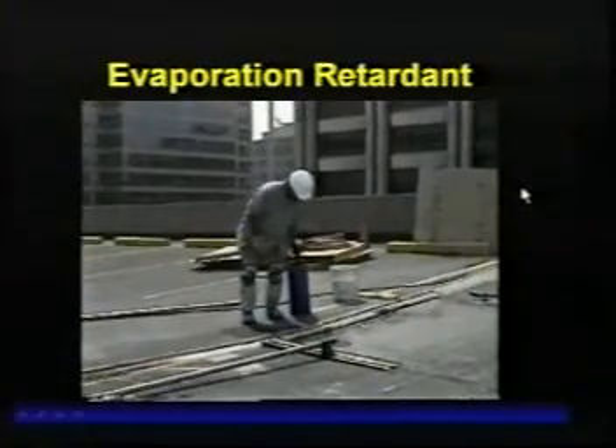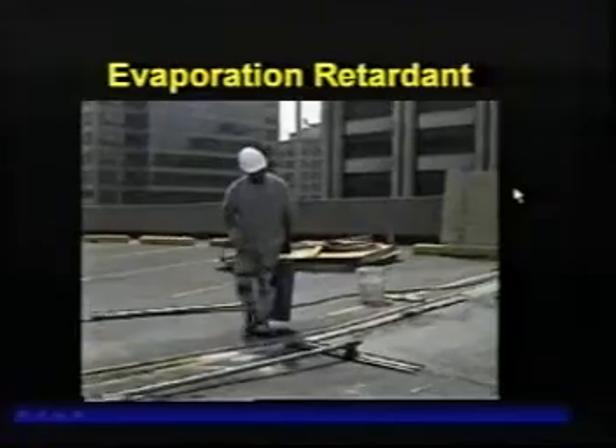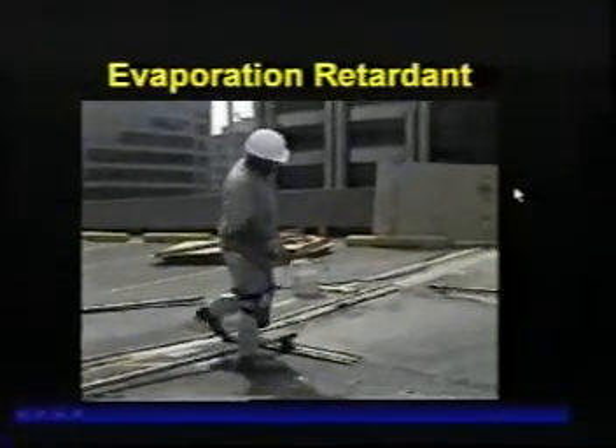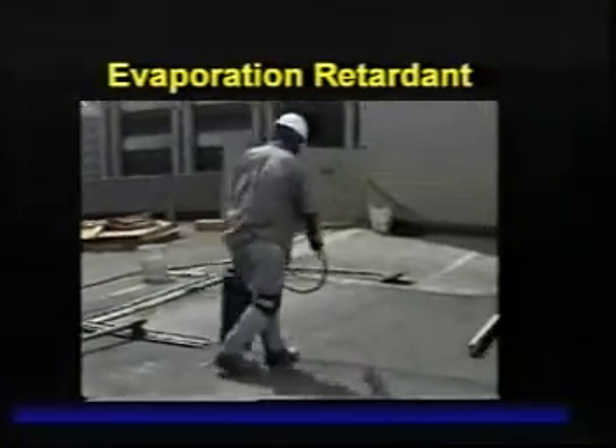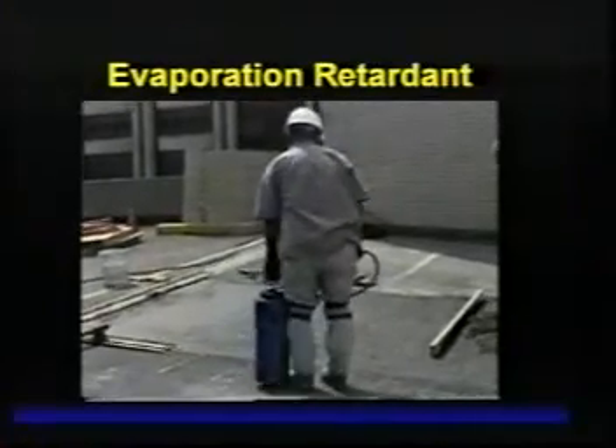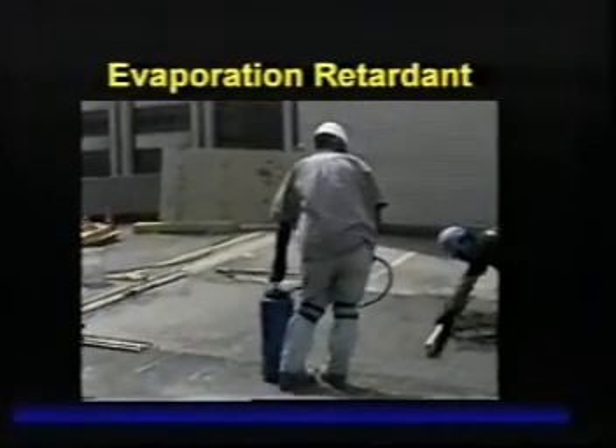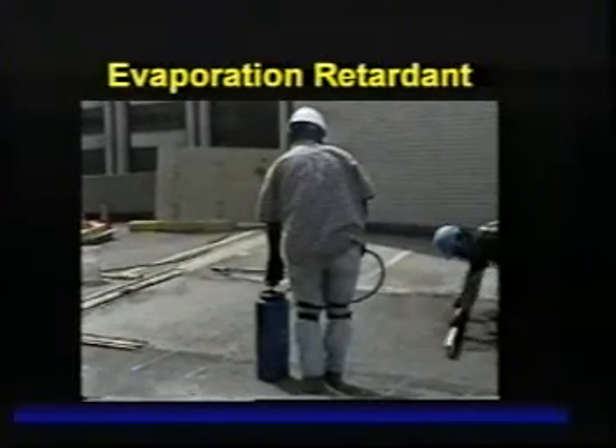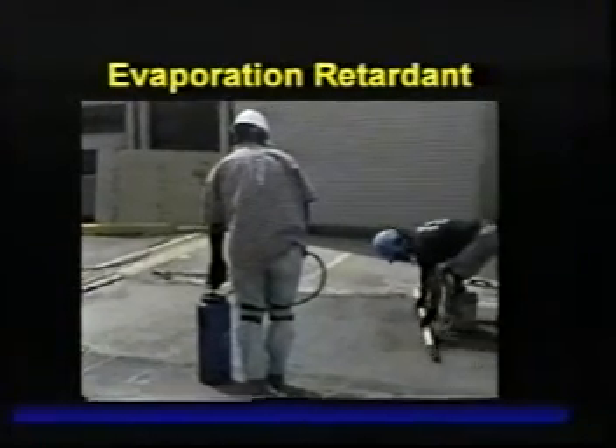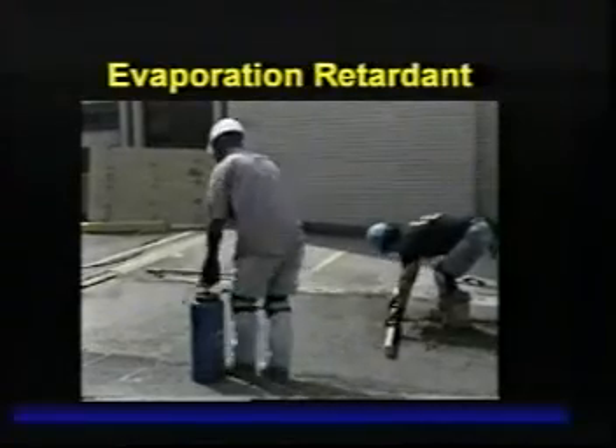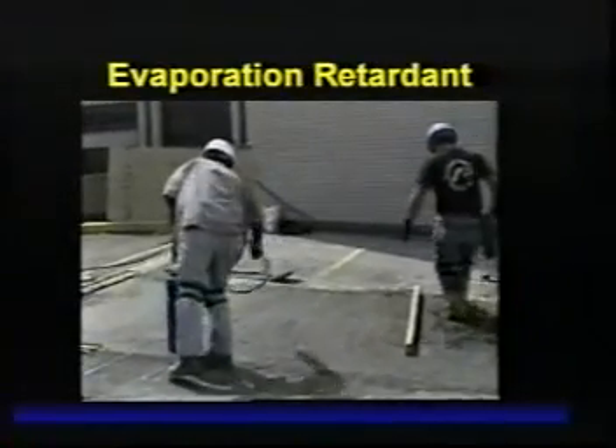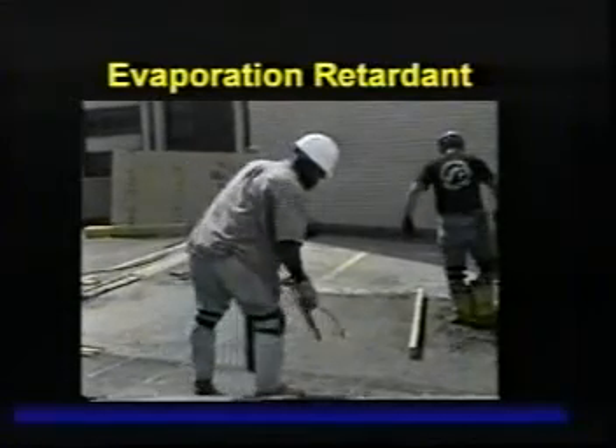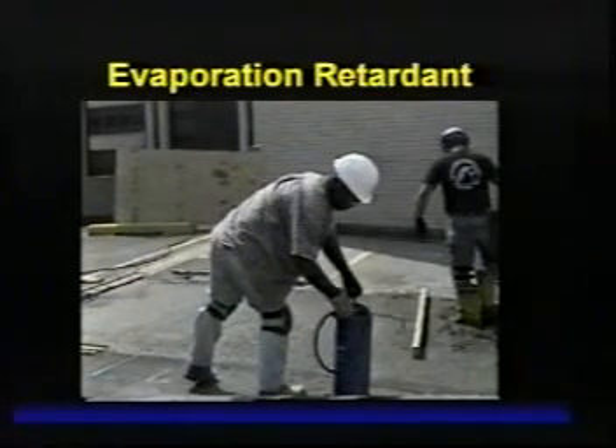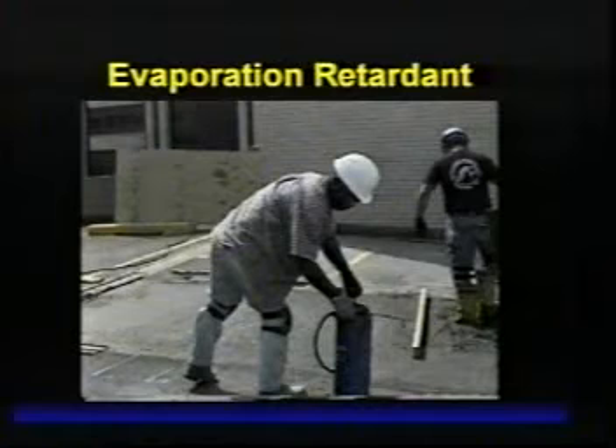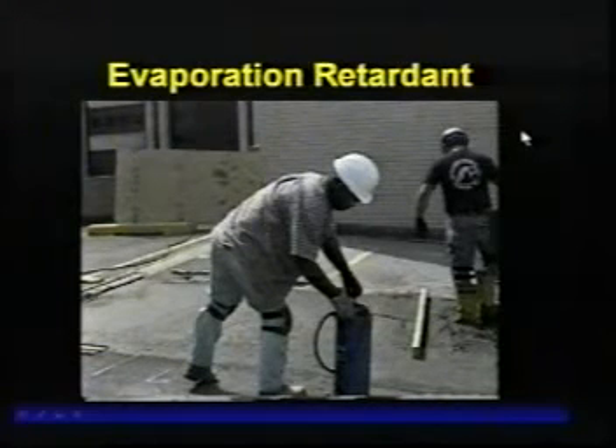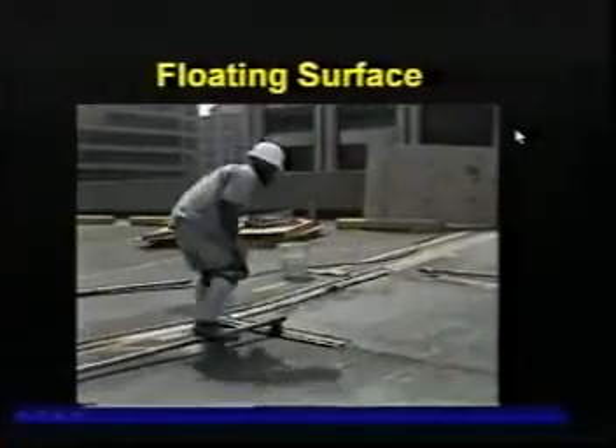The next step, and I've got some steps in here that may not be required, but in hot weather, after the initial screeding, an evaporation retardant is placed on this material, only because sometimes in thin repairs, horizontal repairs, if it's hot and windy, you could have rapid evaporation and plastic shrinkage cracking can take place. So immediately, this product, I guess, was developed sometime over the last 10 years or so. It's a great product for this type of application where you have thin repairs that are susceptible to plastic shrinkage cracking. Then the next step is floating.